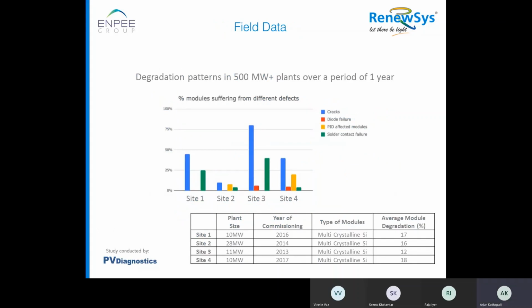In another study, this is from field data in India, degradation pattern in a 500 megawatt plant for a period of 1 year. The study is basically conducted on 500 megawatt plants at different locations for a period of 1 year. In that, they noticed almost all the sites are having cracks. When we say cracks, these are EL cracks, and diode failures, PID affected modules, solder contact failure, that is nothing but a solder joint failure. This is the broad study, and most of the sites saw that cracks are more.